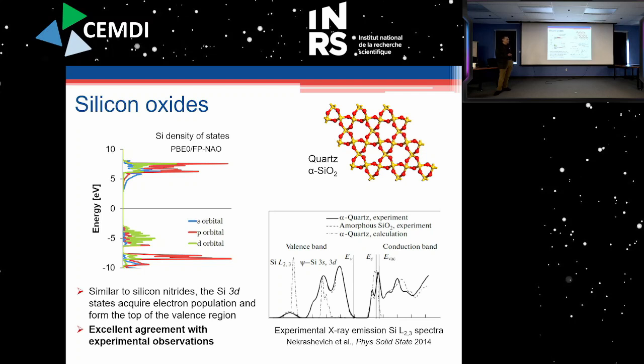And what is nice about quartz, at least in the context of our work, is that there are what I call orbital resolved X-ray emission spectra available that show that indeed the 3D band of the silicon is involved or can be observed in the structure of quartz silicon oxide. So basically our finding of the involvement of the 3D states in condensed phase matter is actually in agreement with what is observed for silicon oxide.